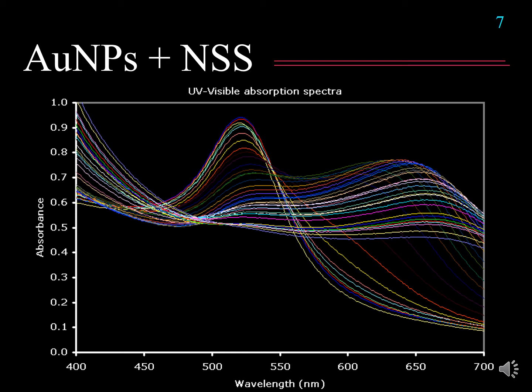So what you can see here is a scattering mode on the right hand, and because this is about 600 something, that light was scattered, so at the end we can see that our colloidal solution has changed color from red, from the absorption at 520, to a kind of bluish color, because of the scattering at about 600 something nanometers here.